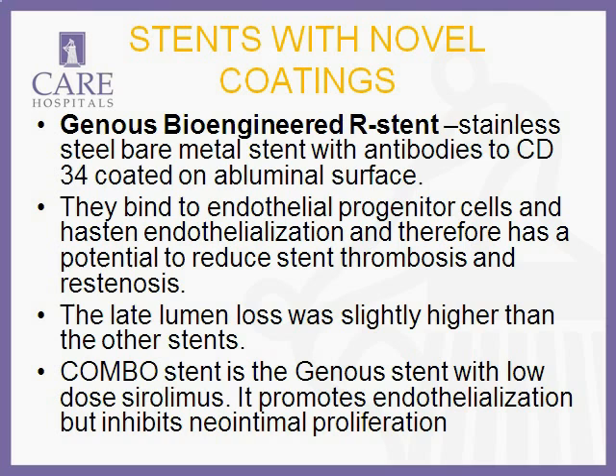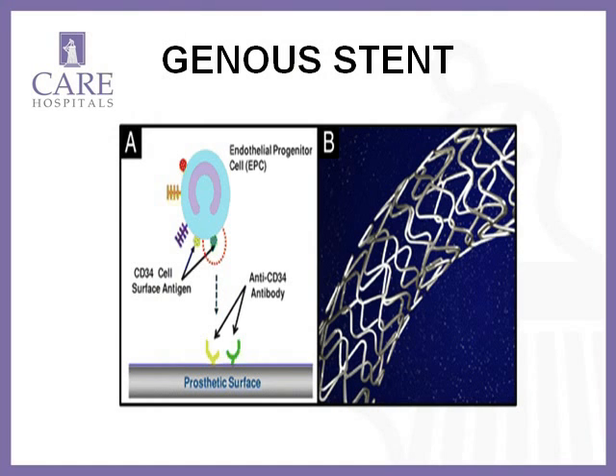Now, this is the Genous bioengineered R stent, which is a stainless steel bare metal stent coated with antibodies to CD34 on the abluminal surface. They bind to the endothelial progenitor cells and help in faster endothelialization, and therefore reduce the potential of stent thrombosis and restenosis. But the stent has been shown to have a late lumen loss, and therefore it has been improvised into a combo stent where it has been combined with sirolimus, which inhibits neointimal proliferation.